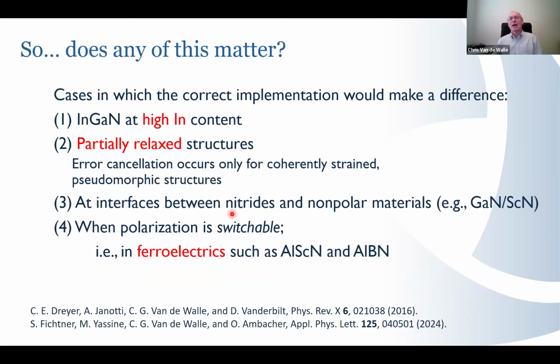And you can wonder, well, if the values in the end are so close, why should we worry? Well, let me give you 4 reasons, and I'm sure there are more, why we should do the right thing, because this does matter. There are cases where these errors will actually not cancel so well and give you incorrect values. For instance, if you have large strains, people are very interested in InGaN with high indium content for red LEDs. The larger the strains are in these structures, which is going to happen at high indium content, the larger the error that you make. So not a good idea to do it incorrectly. If you have partially relaxed structures, the errors no longer cancel, and you should really be doing it correctly.